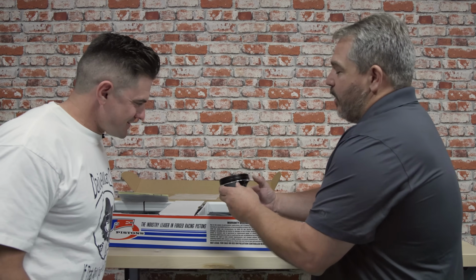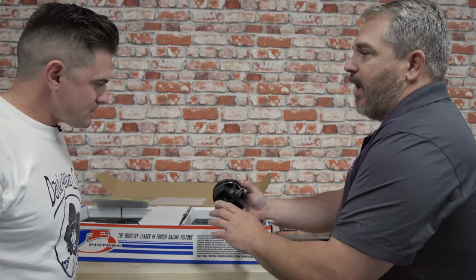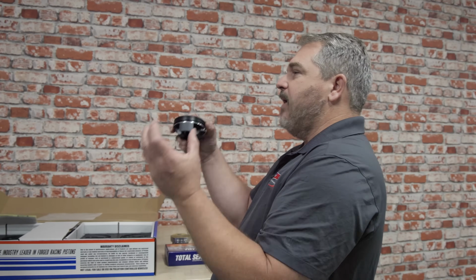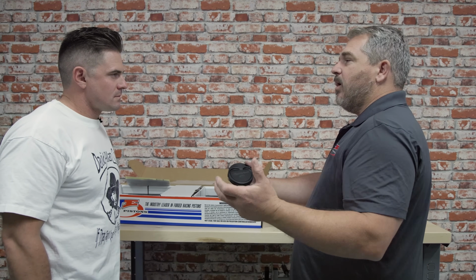Okay. We're doing you a huge favor by making that happen right here. I appreciate that. But one of the things you have to realize is when you do hard anodizing, it basically forms an eggshell around the piston because it's a thin 2,000ths layer around the bare aluminum. Imagine you have an egg, you heat it up, you cool it down, the inside gets hot. If you put a bunch of heat into the anodizing and it never comes out, you're going to heat cycle and put a lot of heat into the bare aluminum underneath the anodizing, and it can get softer over time faster.